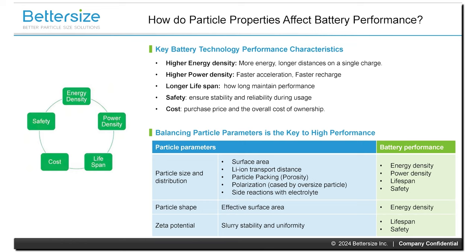Particle shape influences electrode packing density, ion diffusion pathways, and mechanical stability. Spherical particles typically pack more densely and evenly, and this promotes uniform ion transport and reduces stress-induced damage during charge and discharge cycles.